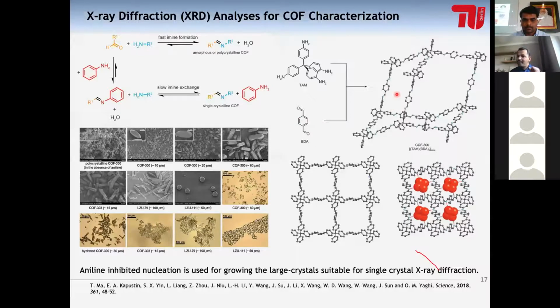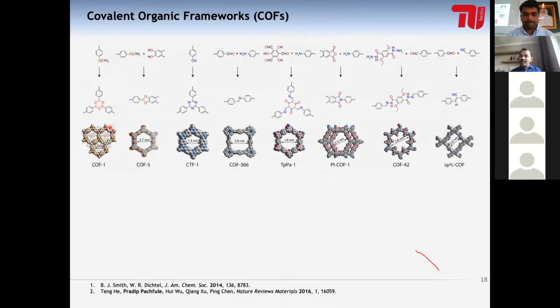sitting. Even more interestingly, when this Schiff-base reaction happens, there are some water molecules which are left out in the reaction. So now we can predict that these water molecules can be sitting in the pores, which were seen in the single crystal analysis of these materials. So this way we can predict the properties of materials, as well as know where exactly these materials can be applied. So in this way, not only the boronic acid trimerization reaction or boron ester formation reaction, but different reactions.